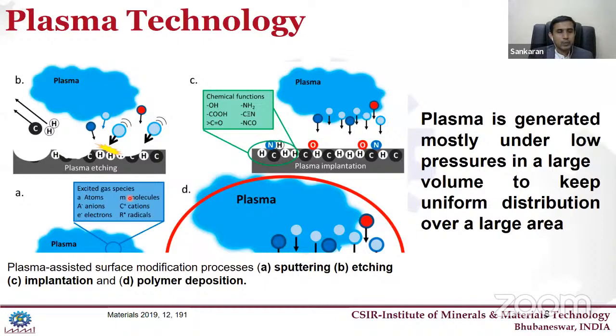Suppose you would like to fabricate nanostructures. We can follow plasma technology, which is a dry plasma etching technique without any chemicals. We can etch and make nanostructures, and we can control the plasma conditions to get very uniform or various nanostructures. Also, plasma can be applied for implantation purposes.